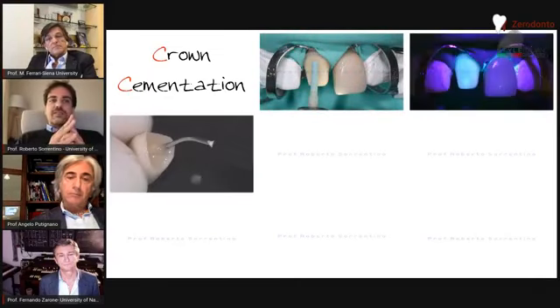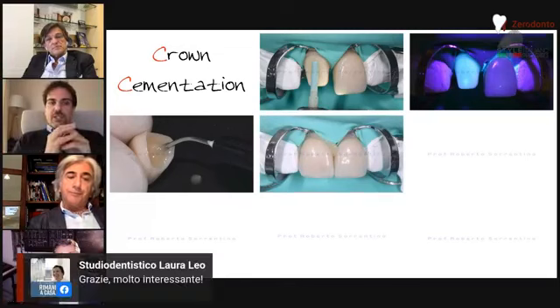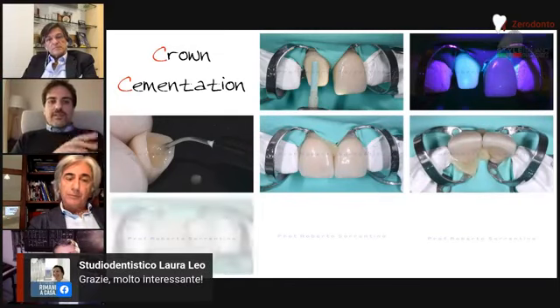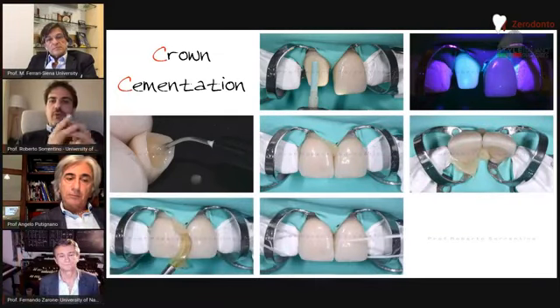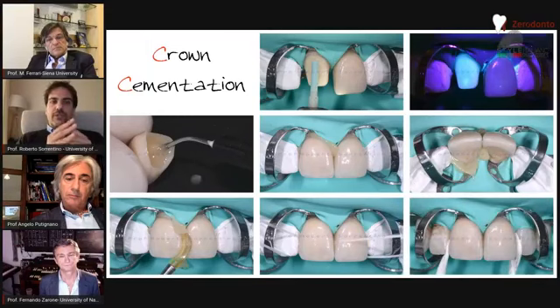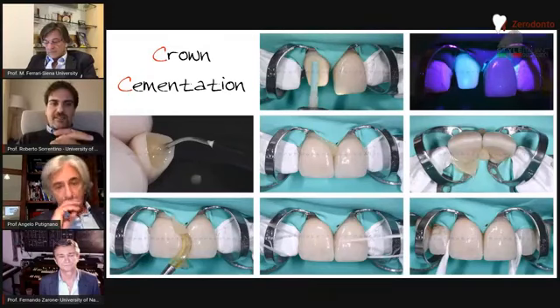Differently, I used a simplified adhesive protocol with a self-etch approach for the crown, since it had good primary retention. And although complete isolation is not mandatory when you go for simplified cementation of full-coverage crowns, the use of rubber dam makes cementation faster, easier, and much more precise. However, it's just my advice.